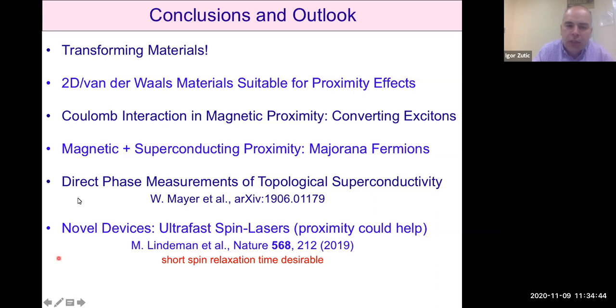If we were to consider both magnetic and superconducting proximity effects, it may be possible to even realize Majorana fermions, and recently we were involved in direct phase measurements of topological superconductivity, which is a platform that hosts Majorana fermions. In terms of novel devices, there may be a possibility that these magnetic proximity effects could allow us to envision applications that are room temperature, but not limited to magnetoresistive effects. And we recently were working on a class of ultra-fast spin lasers where surprisingly short rather than long spin relaxation time was desirable. So if I have another minute or two, I would then mention some of these possible directions. But if we are running out of time, I can stop here as well.